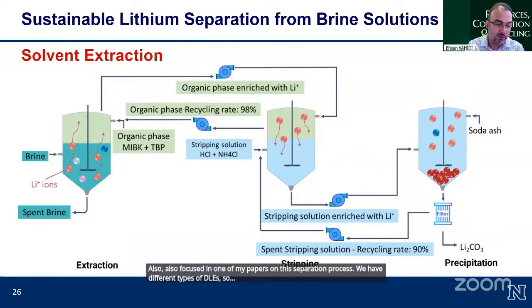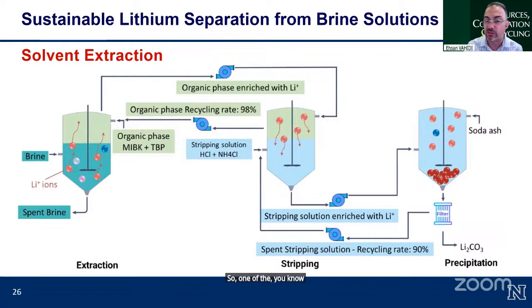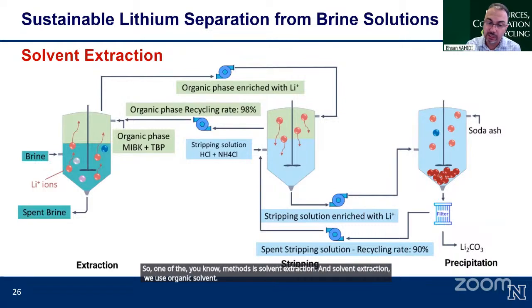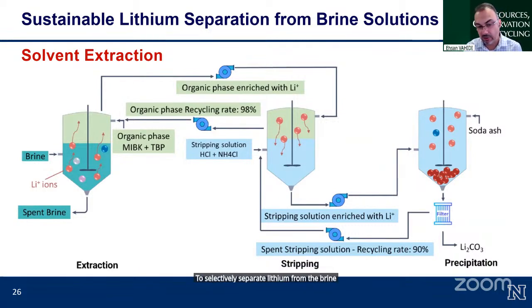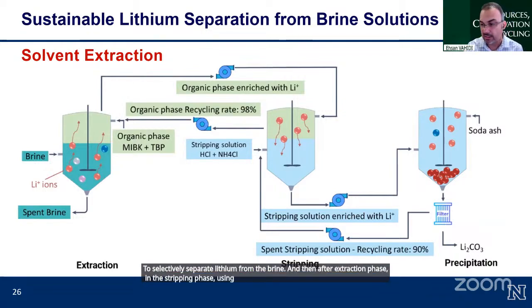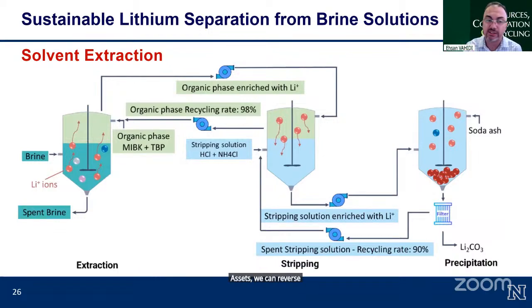Whatever we modeled was based on one processing plant, the pilot plant that we got the results from a company. But we started to compare different production systems in DLE processing. One of the methods is solvent extraction. In solvent extraction, we use organic solvent to selectively separate lithium from the brine. Then after the extraction phase, in the stripping phase, using some acids, we can reverse the reaction to separate lithium from the organic phase, and then concentrate lithium in the system.